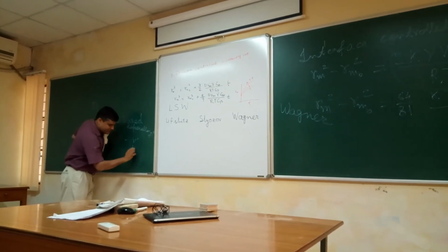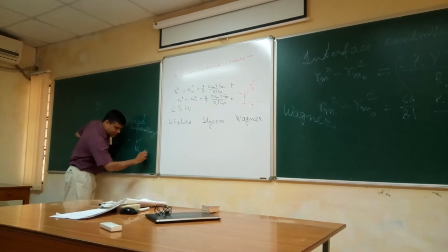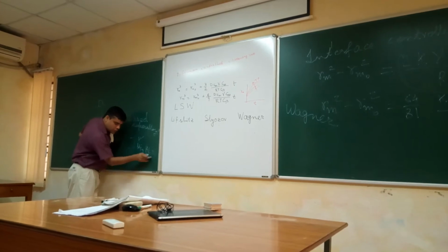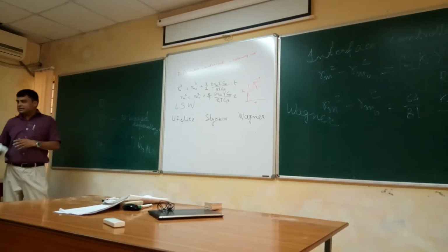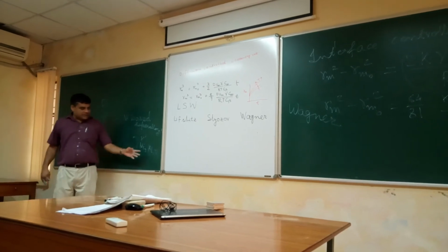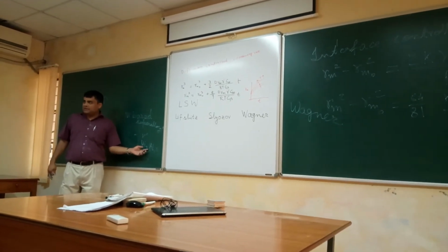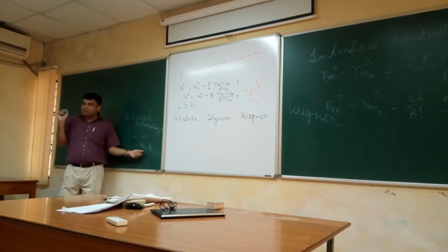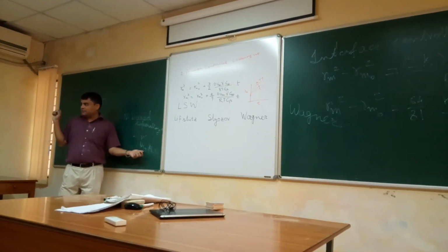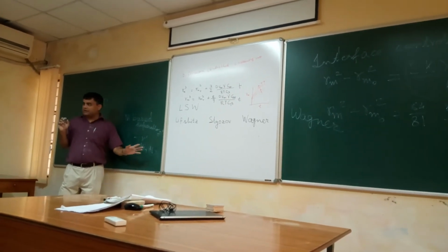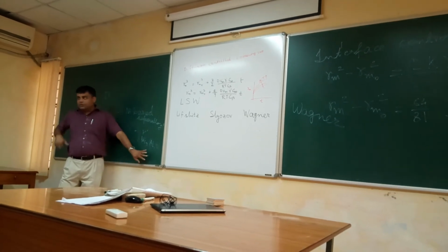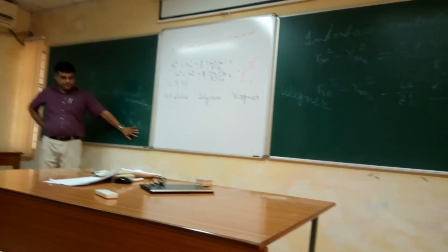Gamma prime is Ni3Al, primarily Al, but titanium and other elements can also go into that sublattice. The gamma prime unit cell is FCC-like: nickel goes on the face center positions, and aluminum or titanium on the corner positions. So the Bravais lattice is no more FCC, but simple cubic. That is the structure of gamma prime.